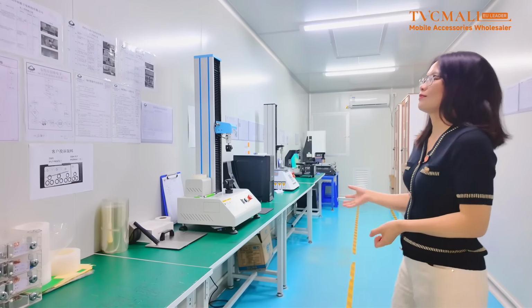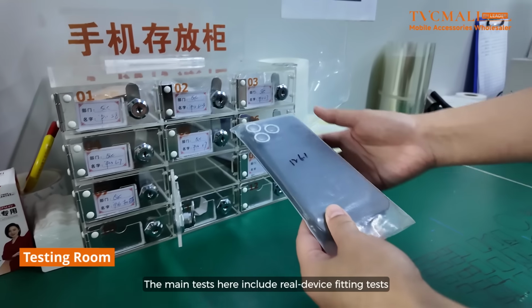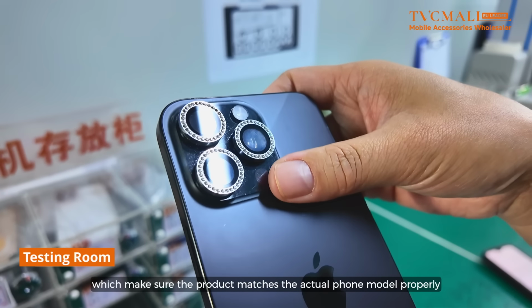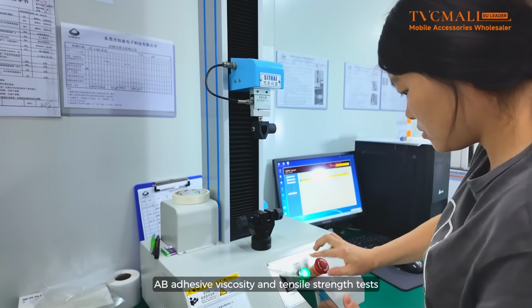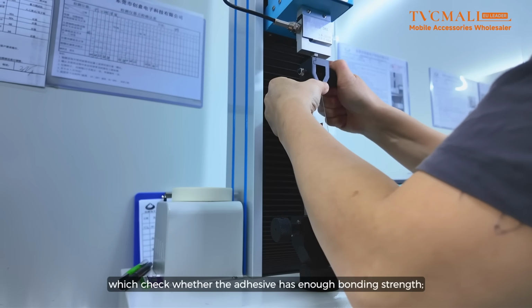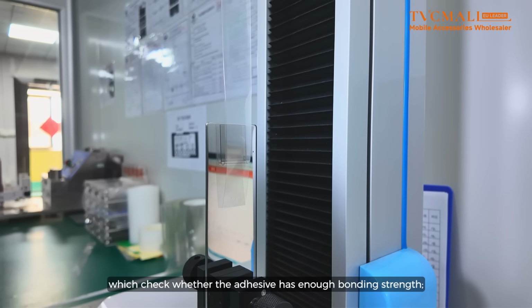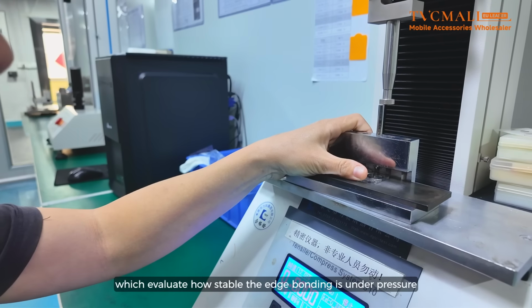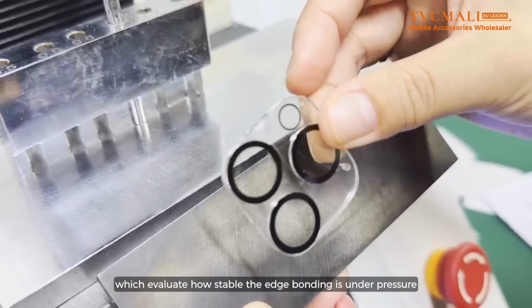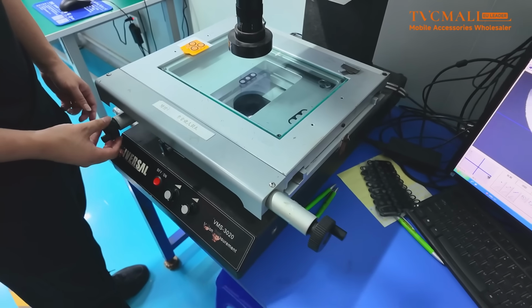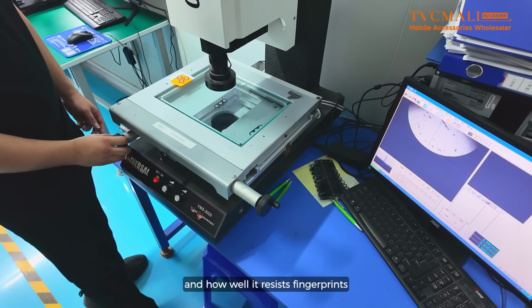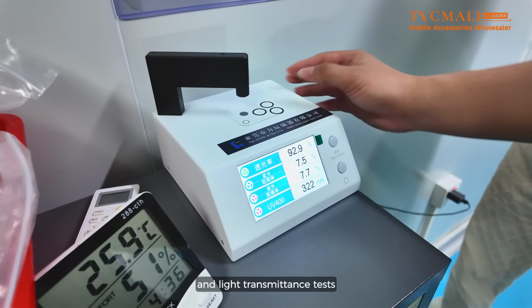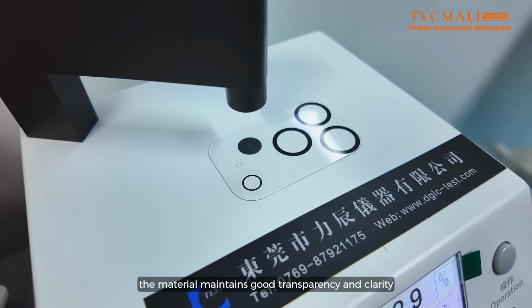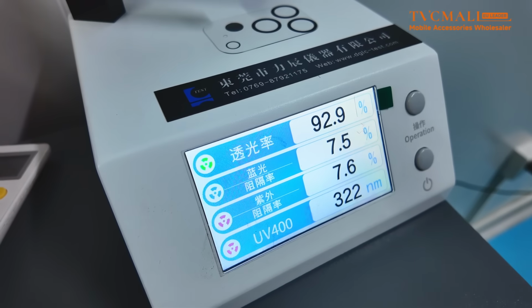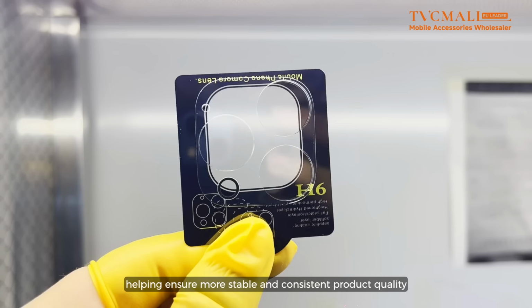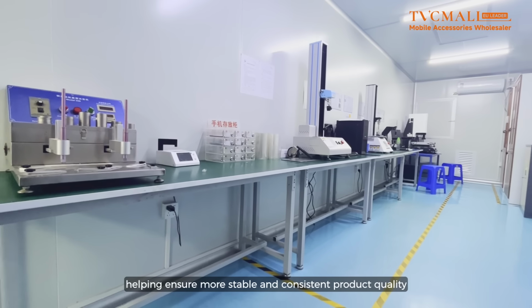This is the testing room. The main tests here include real device fitting tests, which make sure the product matches the real phone model properly, AB adhesive viscosity and tensile strength tests, which check whether the adhesive has enough bonding strength, edge pressing tests, which evaluate how stable the edge bonding is under pressure, water contact angle tests, which show how smooth the surface is and how well it resists fingerprints, and light transmittance tests, which help confirm that the material maintains good transparency and clarity. Each step is backed by clear data, helping ensure more stable and consistent product quality.